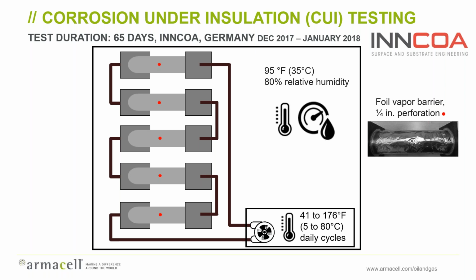They insulated those pipes with different materials and they pierced the insulation halfway through with a 1/4 inch hole and then just let it go for a couple of months to see what happened. So basically, when you're in the high humidity, warm environment and the pipe goes cold, you get vapor traveling towards the pipe, you get condensation forming on the pipe, and everything heats up inside the pipe and that water evaporates. So you're creating a cycle that's kind of the worst case for corrosion under insulation. So after that 65-day test period, they disassembled and had a look to see what had happened.